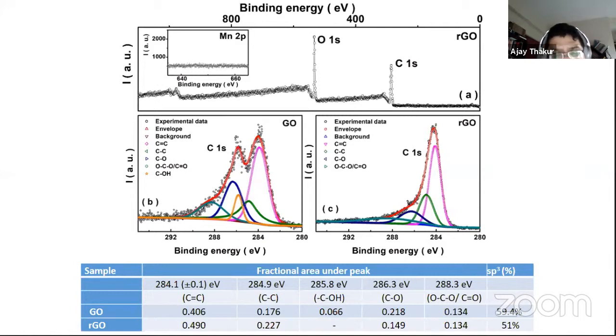obtained was high. Another point which beginning researchers in this area have to be careful about is whenever you are comparing XPS data, trying to estimate the sp2 fraction. XPS data essentially talks about the binding energies for various types of bonds. For example, there would be something corresponding to C double bond C, something corresponding to C single bond C, something corresponding to C single bond O, and so on. By looking at the area under the curves for these respective peaks, one can differentiate between the pure sp2-like carbons and sp3 carbons. So the ratio of sp3 carbons to sp2 carbons can be obtained using XPS.